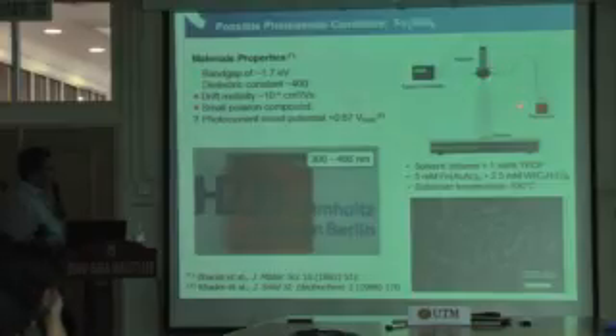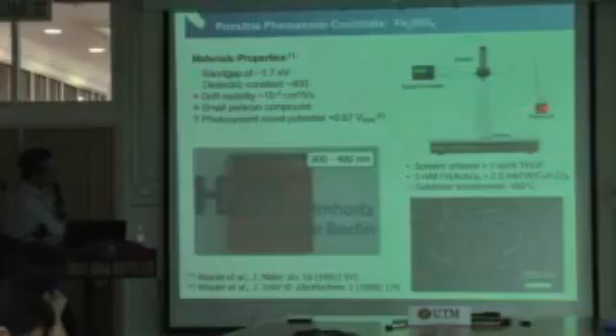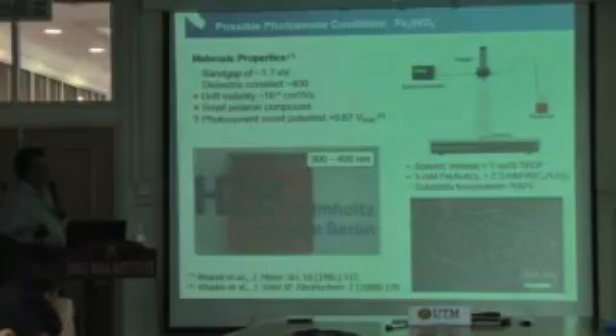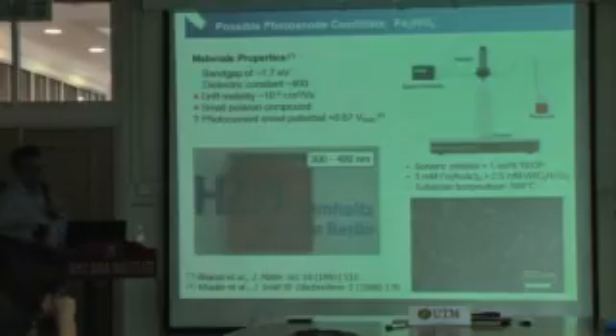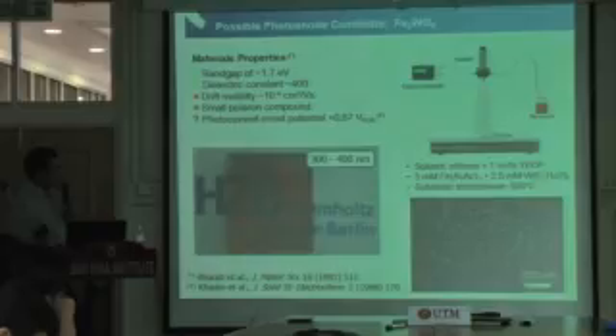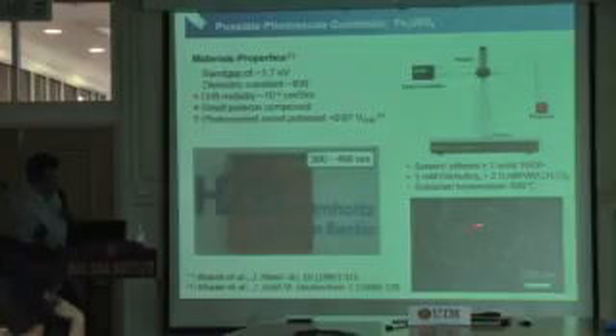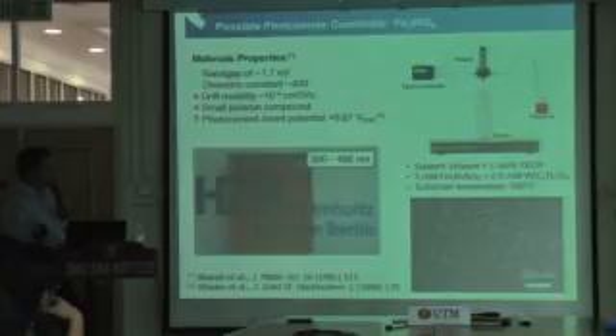And so we started to look into this material. We made it again by our spray pyrolysis, taking the precursors iron and tungsten in a liquid solution and spraying it onto our sample. We get this brown color film, which already indicates good absorption, because brown means it absorbs far into the visible spectrum. I don't know if it's really clear, but the films look kind of grainy.